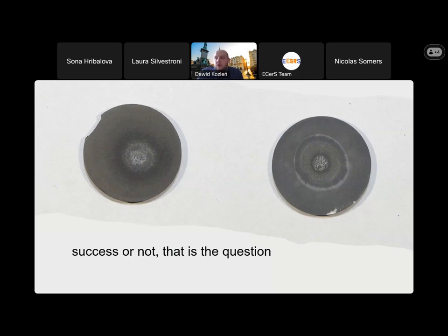We need to work more on these 2 or 3 different composites that are showing you the use of reactive sintering during the sintering. You can imagine that this material was synthesized at a temperature lower than 1400 Celsius degrees, but it was working at 1800 Celsius degrees. That was quite good for us. Now we are waiting for some patents, so after that, I can publish the results.